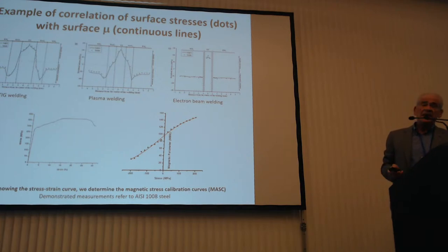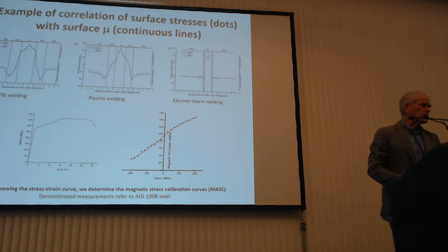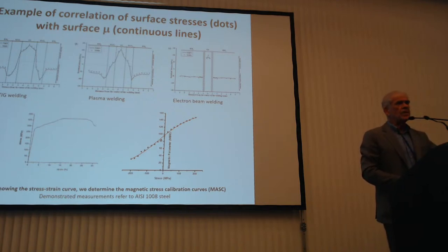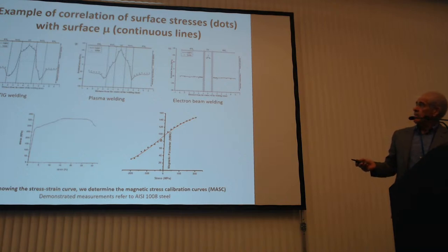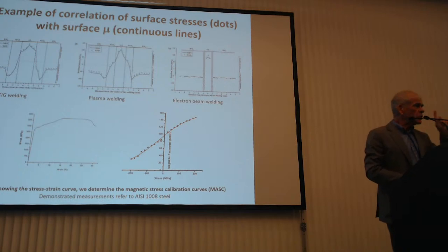The continuous lines represent the magnetic permeability and other magnetic properties. You can see how nicely the magnetic measurements are in agreement with the residual stress reference method of measurement. Therefore, we can use the magnetic characteristics or the magnetoelastic characteristics as the transfer standard for monitoring the residual stresses in the field. And actually, bearing in mind this pair of values, we can generate what we call magnetic stress calibration curves, each one of them corresponding to its different type of steel.